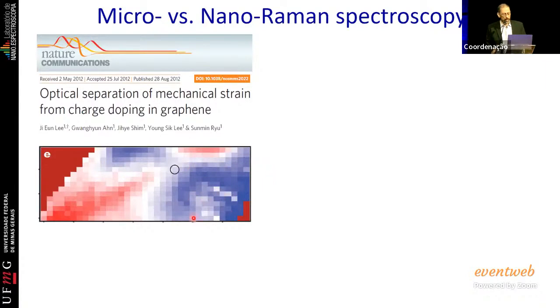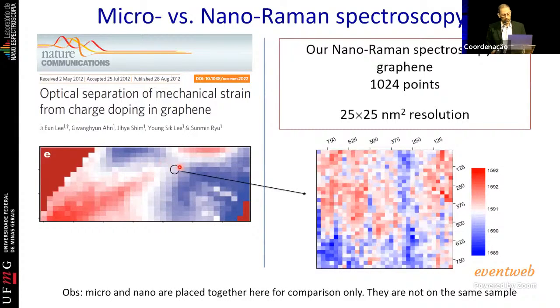And they show that when you have graphene sitting on a substrate, the graphene is naturally showing inhomogeneity in the strain and doping all over. Okay, but this was made with a microscope. So every pixel here, the distance between one pixel and the other is 1 micron. And if you go to this one pixel here and you look with the nano optics, you see that at this 1 micron location, you also have inhomogeneity, but now you are looking at the nanometric level, okay?